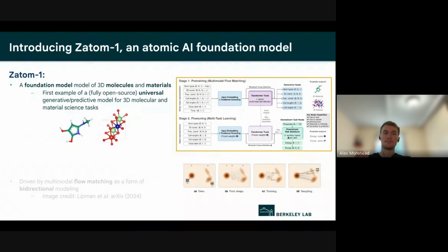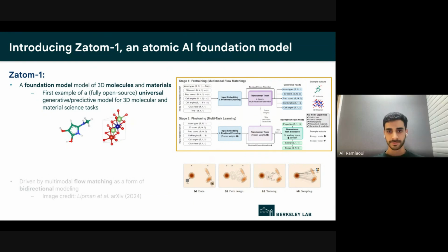And at the end of that, you just read out the modalities that pertain specifically to materials. In this case, that's atom types, fractional coordinates, cell lengths, and angles. Then we construct a material using PyMatGen. So essentially, we're explicitly telling it to generate a material, and then we're just reading out the modalities specific to materials. Very clear. Thank you. Yep.